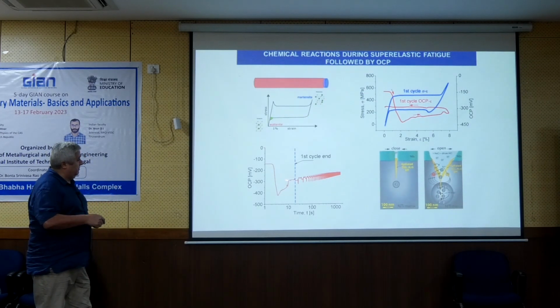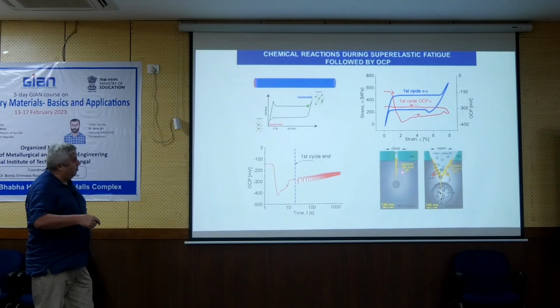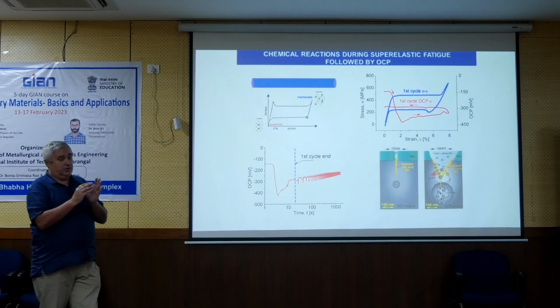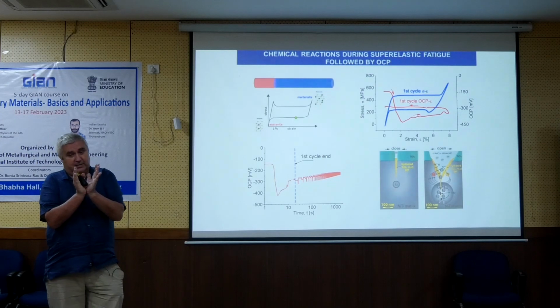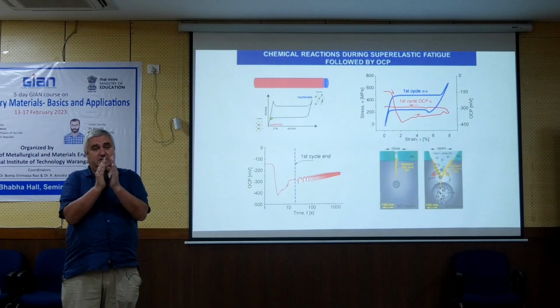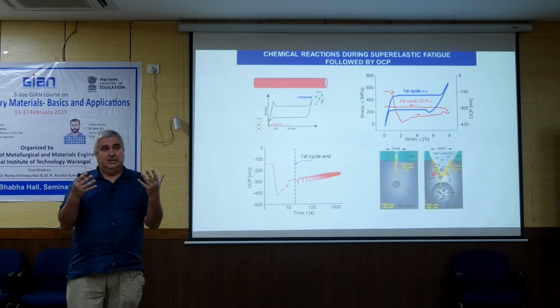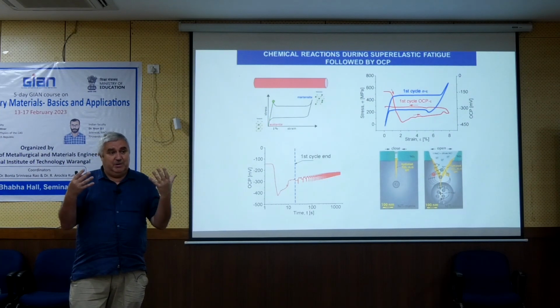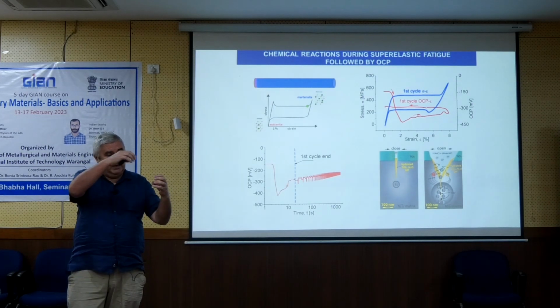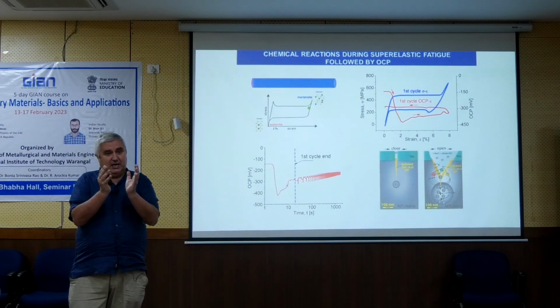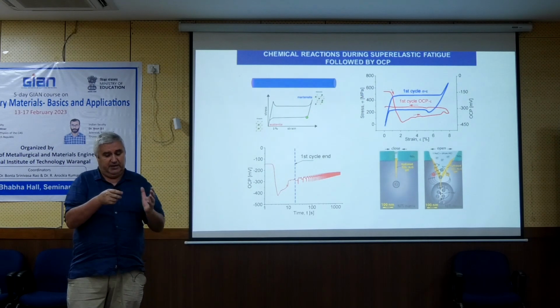So we have a good reason to believe that somehow the corrosion process which proceeds is now localized into these cracks which are opening and closing. If they remain open, there will be no problem. The problem only is if they open and close. So again, there is a problem. What does it mean for the metal if you have a surface covered by such cracks which periodically open and close? We didn't really know.